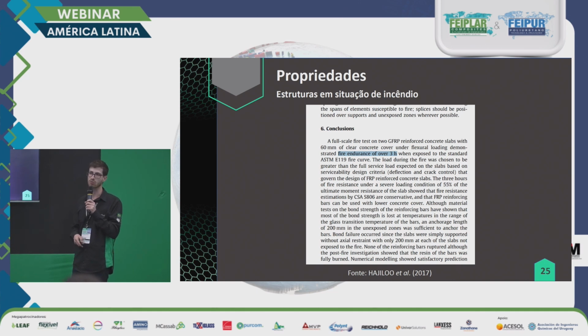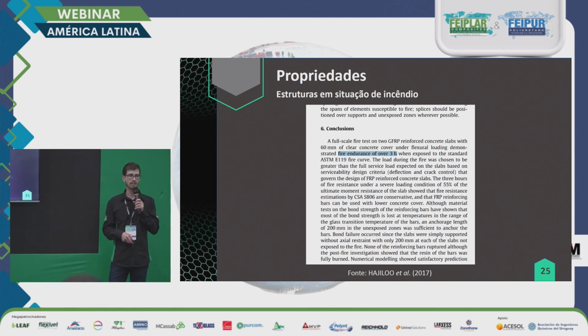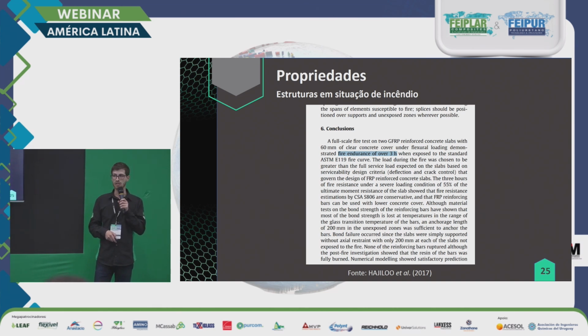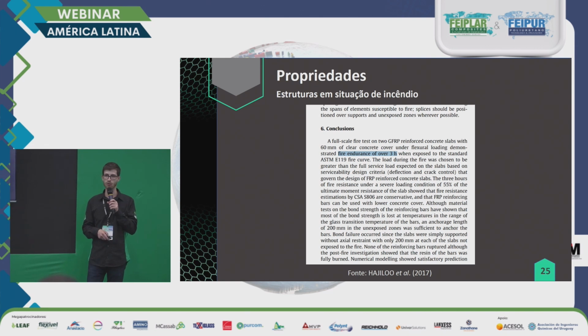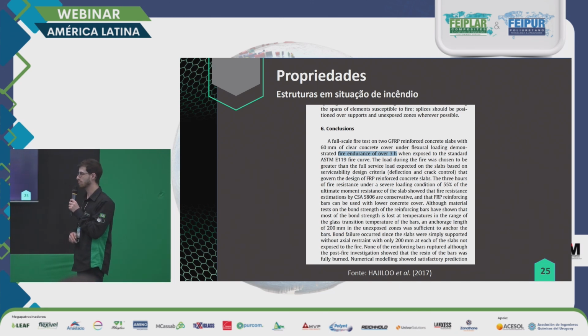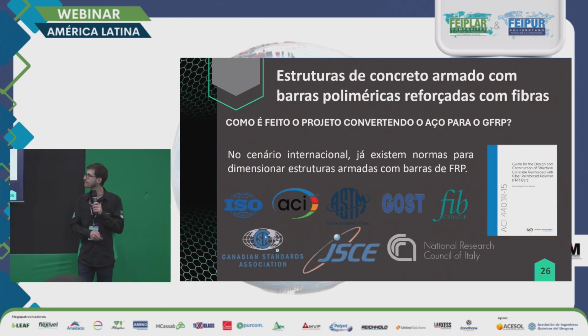So the fire resistance time of this structural element, including composite meshes, was able to hold its properties for more than 3 hours, 180 minutes, and that's according to the requirements in Brazil for buildings and houses or buildings with more than 20 floors. So that would be enough for those inside this building to get out in case of a fire before the structure collapses.